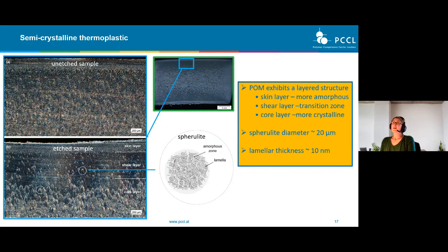So if we take now a closer look at microscopic pictures of the POM, we can see here on the upper side a part of the edge of the sample. We have here once the sample unetched, and down you can see the sample etched. And here we can clearly see that we have a layered structure at the edge of the sample, like the skin layer,